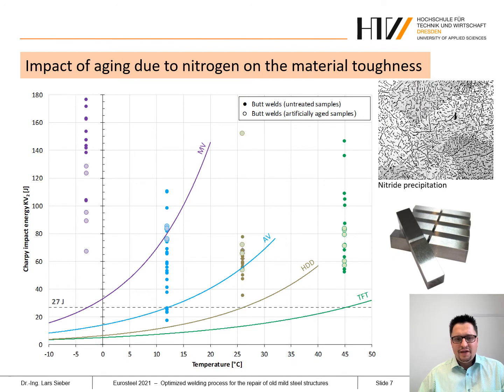As I explained in the beginning, especially the converter steels, the Thomas and also the Bessemer steel, have a high content of nitrogen. The iron nitrides dissolve in the heat affected zones heated above 620 degrees Celsius, and an embrittlement due to the aging process is reversed. It can be assumed that the aging process starts again after welding and the toughness decreases again.